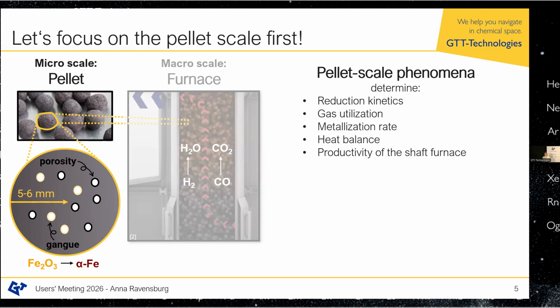We are for now only focusing on the pellet scale because there's a lot of pellet scale phenomena that are very, very important, not only for this pellet scale, but also for the macro scale. And in order to have a reliable process model, you already need to be able to accurately model the pellet scale, because reduction kinetics are highly influenced by the pellets, the gas utilization in the furnace, your metallization rate, of course, and that's what we're talking about, the heat balance, or also the productivity.